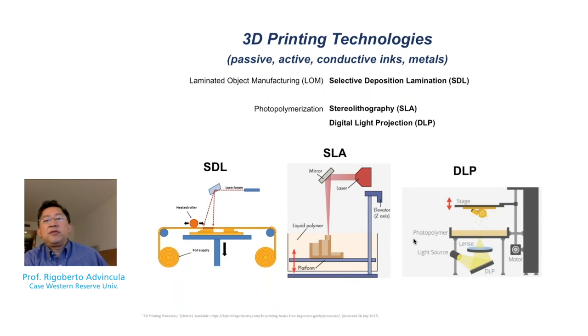photopolymerized, one photon efficiency, such that the photo curing or cross-linking of the resin, whether it's using a digital projection or micro lens with a photo initiator sensitive to light, results really in quite a high resolution of printed material. And it's one of my favorite methods that allow us to look at formulations of the photopolymerizable resin with various metal conducting polymers, carbon nanotubes, or other nanomaterials for fabrication.